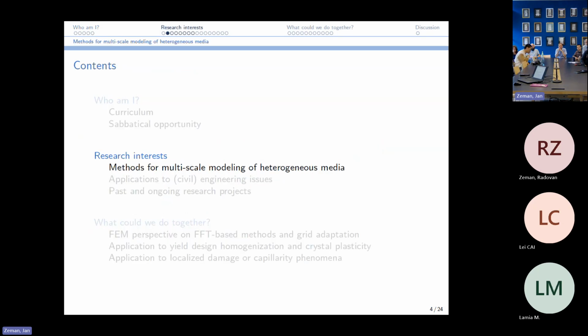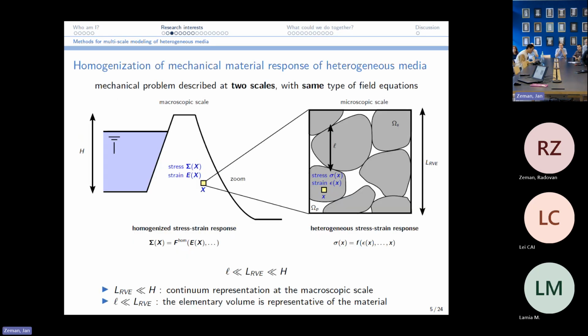So for the research I do, I concentrate on the multiscale modeling of heterogeneous media and often porous media, I would say. So the idea is that when we solve some boundary value problem for a structure at the macroscopic scale, we use a constitutive model, which is actually some average response of the constituents of this material. So for a mechanical problem, you would have the stress and the strain at the macroscopic scale here with capital letters that you use to solve your problem, and their properties stem actually from microscopic features where you have heterogeneous strain and stress response. So depending on whether you are within a grain or in a pore or any type of heterogeneous material, you will have a different response.